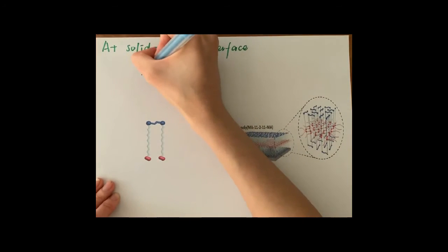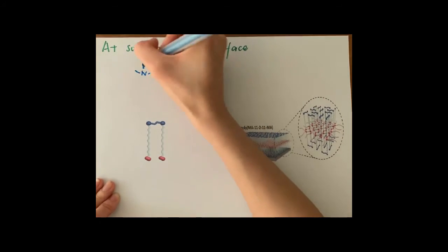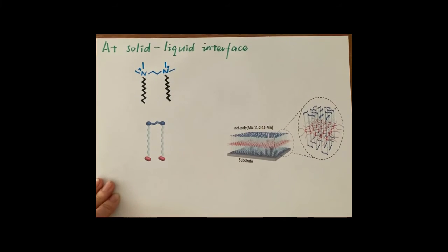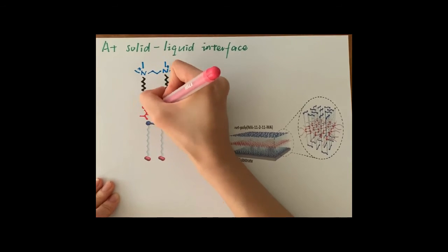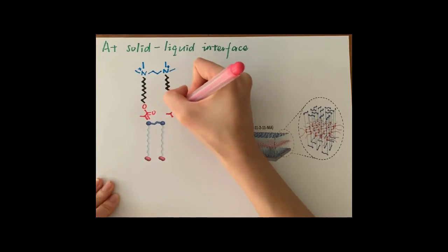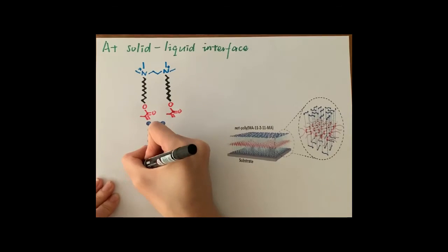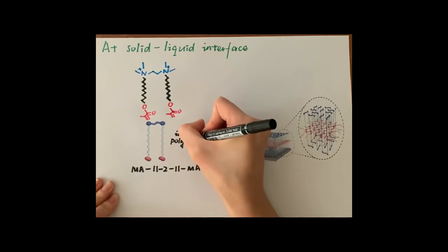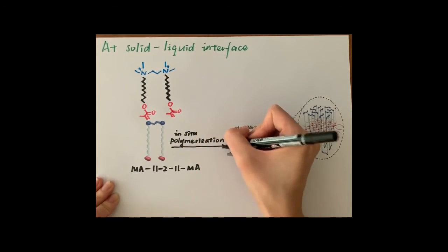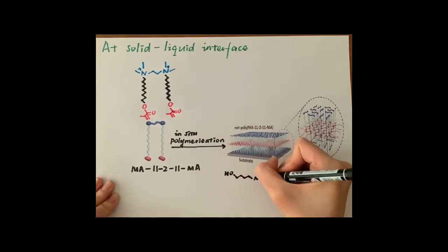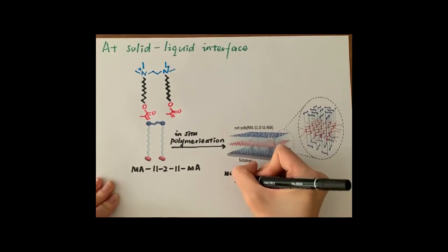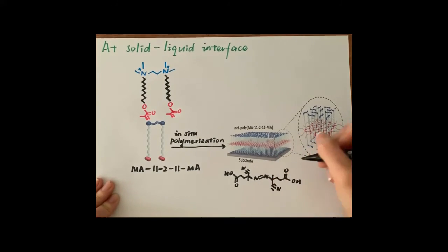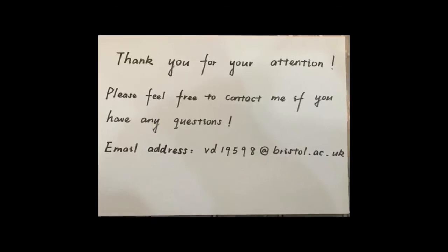The positively charged Gemini monomers MA-11-2-11-MA were initially adsorbed onto a negatively charged substrate through electrostatic interactions. Above its critical micelle concentration, the monomer formed a uniform bilayer covering the solid surface. Then, the bilayer of Gemini monomer was cross-linked using free radical polymerization with a water-soluble initiator. During the polymerization, covalent bonds formed between the methacrylate groups from both upper and lower layers of MA-11-2-11-MA, threading the monomers into 2D networks.